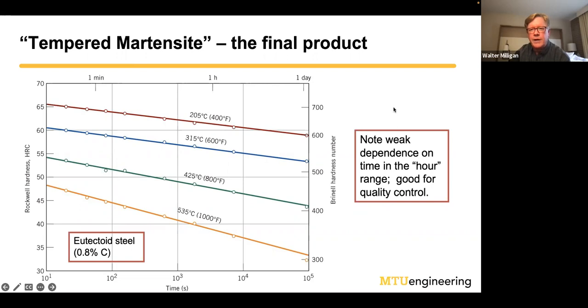I also note over here that if you're doing industrial operations, there's a very, very weak dependence on time. So if you go from 1 hour to 2 hours, the hardness only changes a very little bit. And so that's a good thing if you're doing quality control, because you don't want your thing to get too soft if they left it in the furnace for a little bit too long.